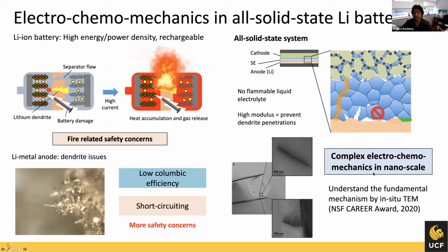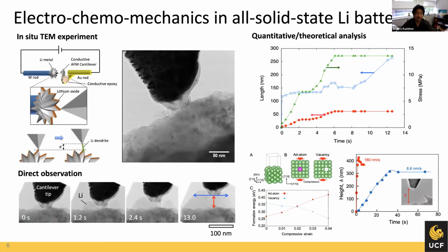So you want to understand this complex electro-chemo-mechanics at the nanoscale, and I've been developing this in-situ TEM technique to directly observe the dendrite growth process and measure the stress or the force that is being applied to the electrolyte. Here we have this setup with an in-situ TEM holder. You mount an AFM cantilever, which is conductive, and you can apply current to grow the lithium dendrite here. So here's one example of the movies.